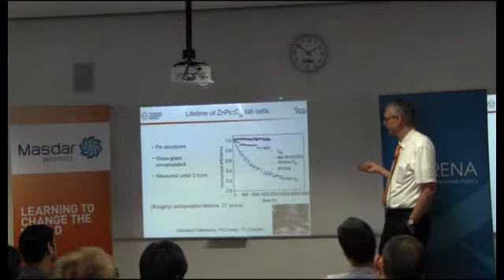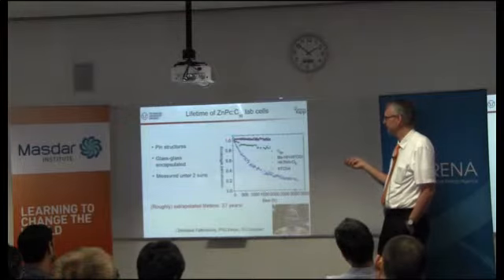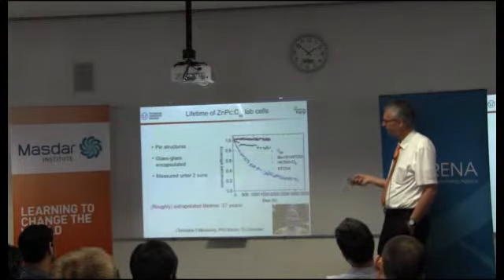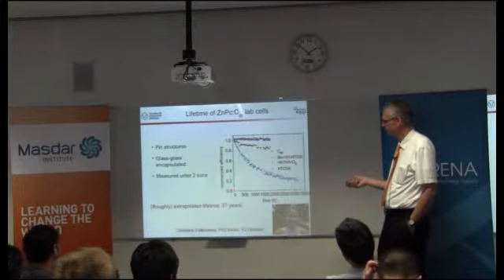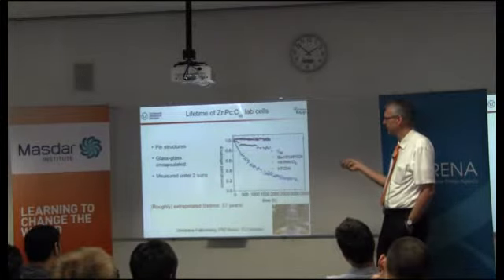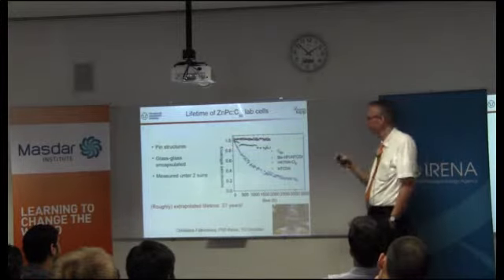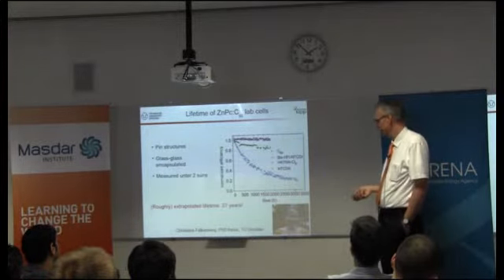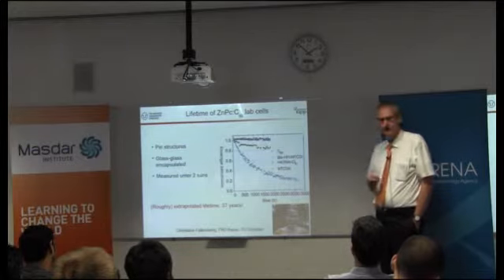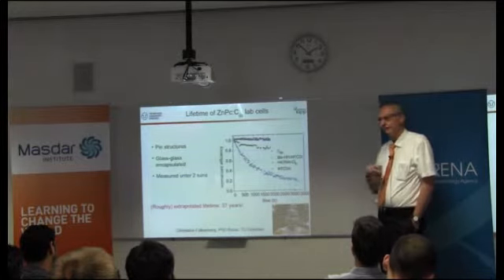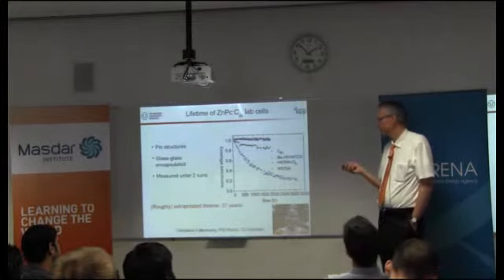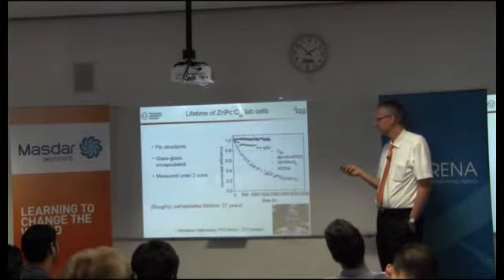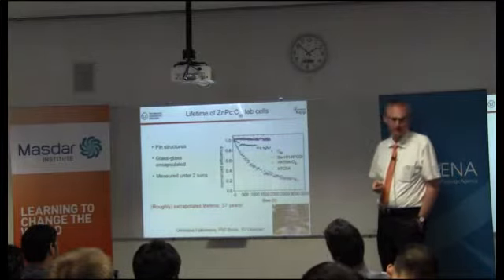Unfortunately, in terms of lifetime, this failed because the C60 cell had the best lifetime. She measured under a simulator of 2 suns for several thousand hours, and the C60 cell basically did nothing. At the end, she extrapolated because, I mean, typically a PhD thesis in Germany takes 3 years, and she couldn't measure long enough. But after 2 years or so, she extrapolated, and she came to 27 years.